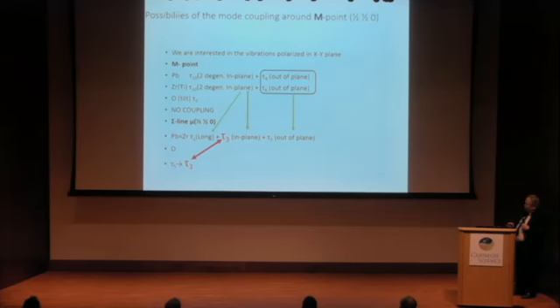So the first question is whether this M3 mode can be coupled to the transverse acoustic mode. Exactly at the endpoint it couldn't be, but as soon as we move slightly aside, it can be. It's shown here that the displacement of lead and titanium at the zone boundary, when we move aside, has a tau 3 component. The same for oxygen: tau 5 is transformed to tau 3. So aside of the endpoint, we can have mode coupling.